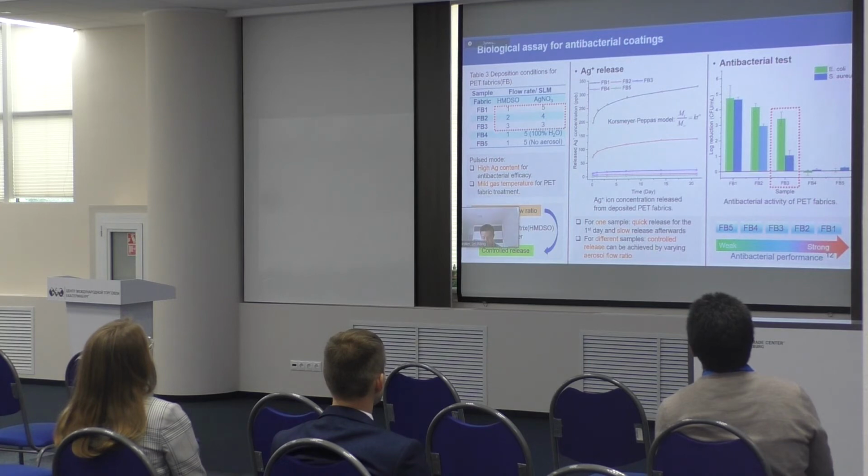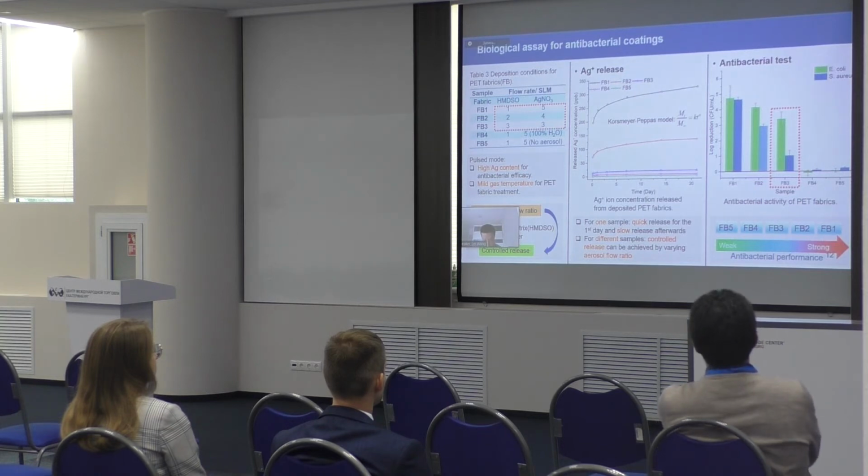Many nanocapsules with thinner shells cannot effectively block the silver ion diffusion into an aqueous environment, while the silver embedded inside the coating and in the capsules with a thick shell can be the reason for the long-term slow release. The release kinetics can be further investigated by the Korsmeyer-Peppas model, and we found it's quasi-Fickian diffusion.